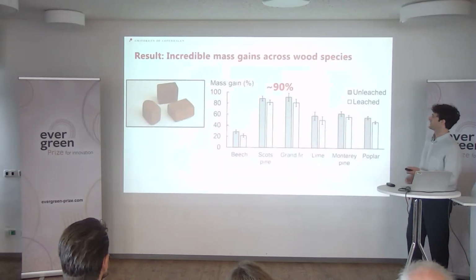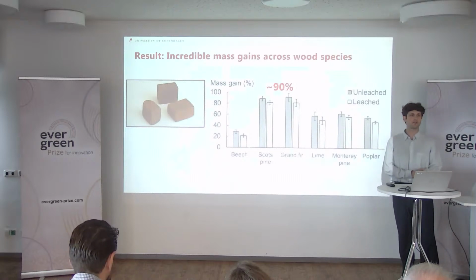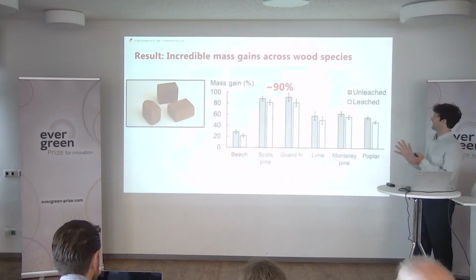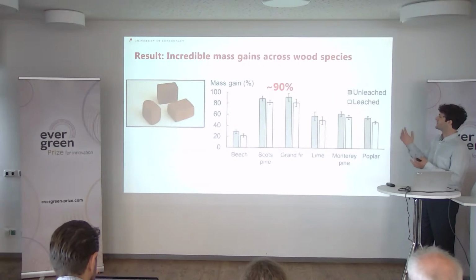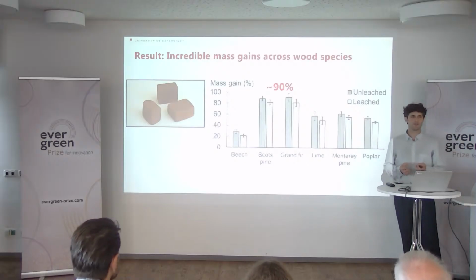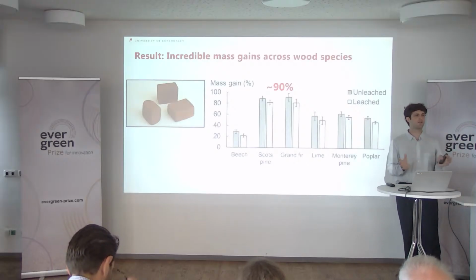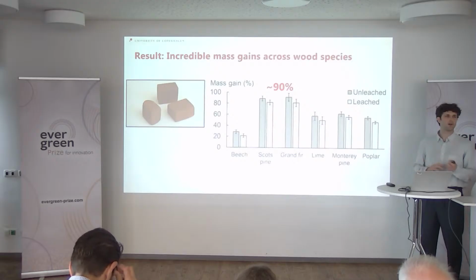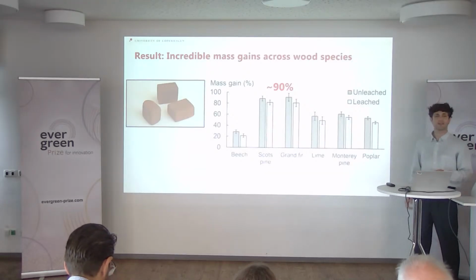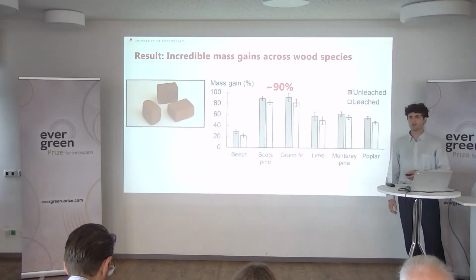But how much lignin did we squeeze into the wood? A lot. So the mass gain was also very surprising and unbelievable at first glance. So we reached almost double the weight in some species. We tested this hyperlignification across several species, broadleaf and conifers, and even after leaching, the lignin stuck in the wood.